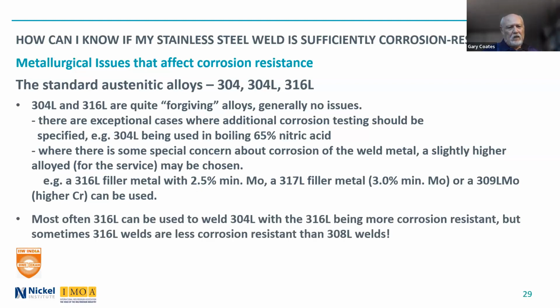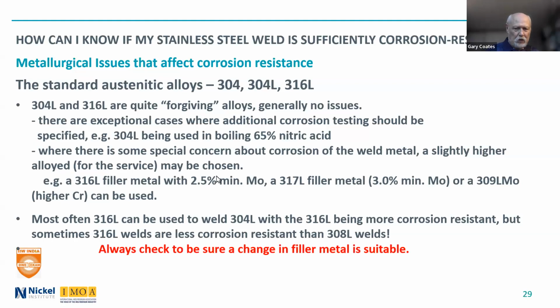Often, can you use 316L to weld 304L? And the answer is most of the time you can, but there are cases where 316L welds are less corrosion resistant than 308L welds. So it's nothing that should be done as a standard, but if there is a particular case, go and ask the corrosion engineer whether it is suitable or not.